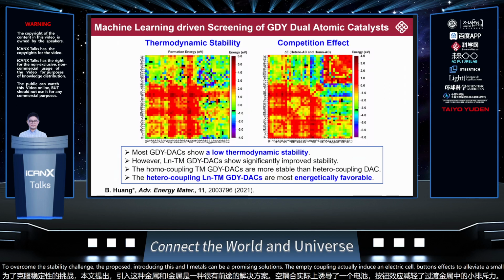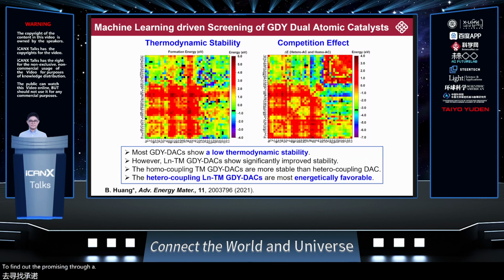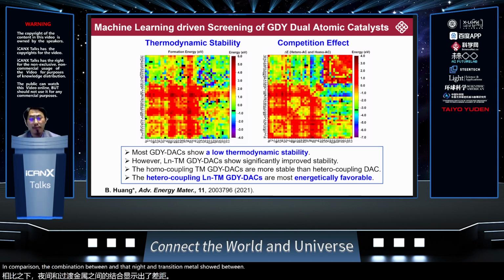pairs. To find out the promising dual metal pairs for experimental synthesis consideration, we have investigated all the 968 combination possibilities between the transition metals and lanthanide metals. As we expected, most transition metal pairs are not stable with large formation energies, especially for the heterocoupling between the different transition metal pairs. In comparison, the combination between the lanthanide and the transition metal shows much improved stability. And this is the most stable selection for DACs.